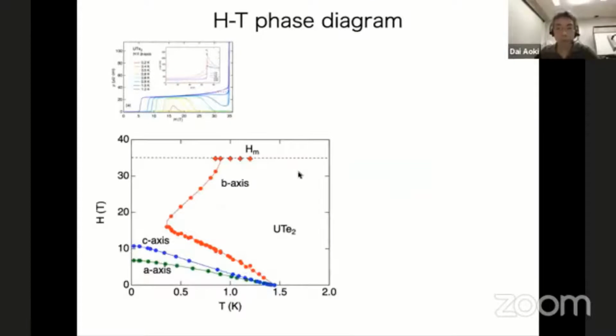So from this, we draw the phase diagram. This is a phase diagram, the HC2 curve for the A, B, C axes. You can see here the A and C axis is 7 and 11 Tesla. But the TC is 1.4, well, depending on the definition, but it's about here.